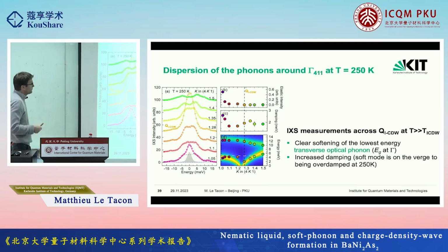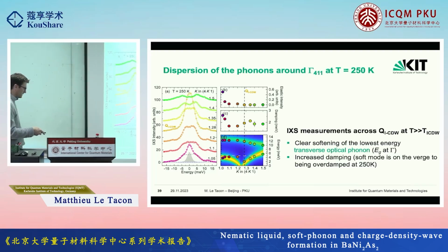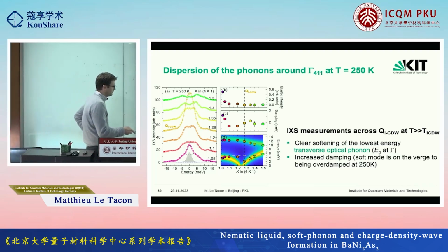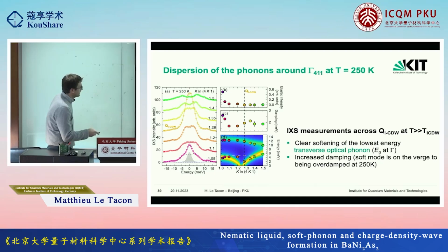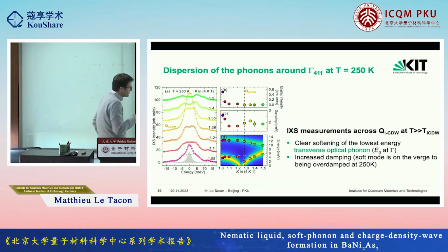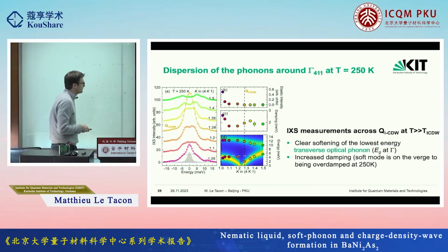Now, we also tried to look at whether there was a soft phonon. So this is in this Brillouin zone, around 411, in the transverse direction from the 411 reflection. So we can basically see it. This is the structure factor that is calculated. So we have an optical branch here. We see this optical branch that disperses pretty smoothly. And then at lower energy, we have this already very soft phonon. So remember, these measurements are done with a resolution of the order of 3 millielectron volts.